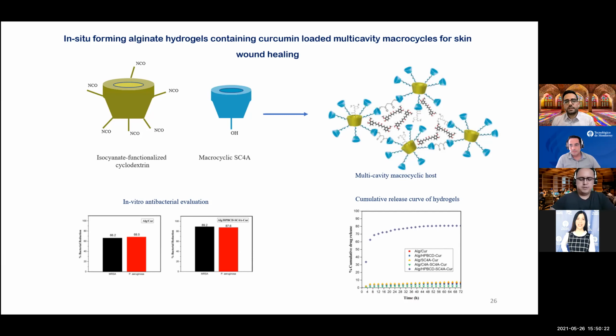Yes, sure. First of all, regarding the alginate, we need to use, for example, calcium chloride, because we need some calcium cations to produce some physical cross-linking between the polymer chains and produce the gels. However, when we are talking about PVA, it has a bunch of hydroxyl groups. We can buy PVA, polyvinyl alcohol, as the hydrolyzed acetate groups, so it depends on the concentration of the hydroxyl groups. Because it has a bunch of OH groups, for producing the hydrogels we don't have any problems. It's again some physical cross-linking based on the hydrogen bonding between the polymer chains.